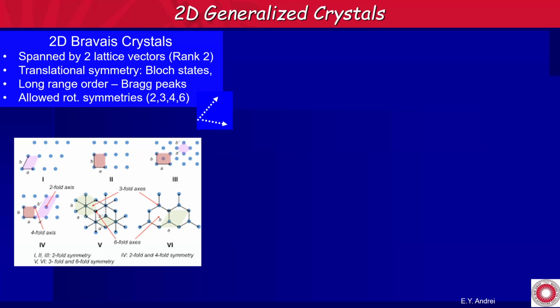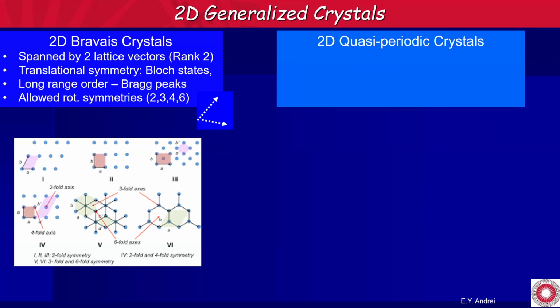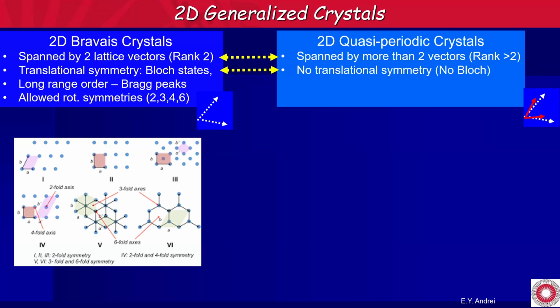Now, what happens when you have quasi-periodic structures? First of all, they're always spanned by more than 2 vectors. It's a rank that's larger than 2. There's no translational symmetry. Therefore, we're losing the main tool of solid state physics, which is Bloch theorem. You have to get around it. No Bloch theorem, no crystal momentum, no band structure. But you still have long range order. That means you still have sharp Bragg peaks, but nothing else.